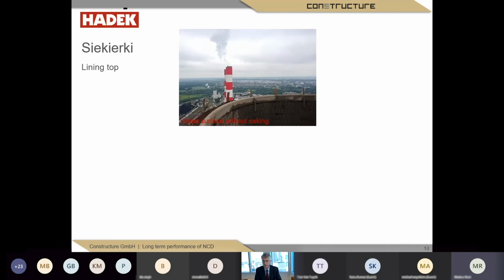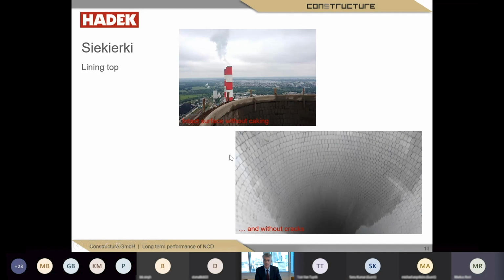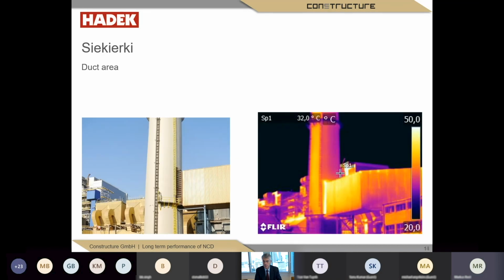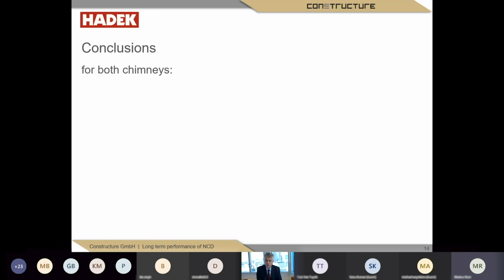As shown, we describe the findings on the chimney analogous to the first one, starting with the very top. You can see here as well an inside surface without caking and also without cracks. Yes, in quite good condition. The thermal imaging we did of the entire chimney, but focused on the duct area, revealed no deficiencies of the inside block lining system. And as I explained before, the hot spots on the chimney are caused by the weaker insulation of the compensator here in the duct area of the chimney. So we found a uniform temperature distribution with no indication of damaged inside surfaces.